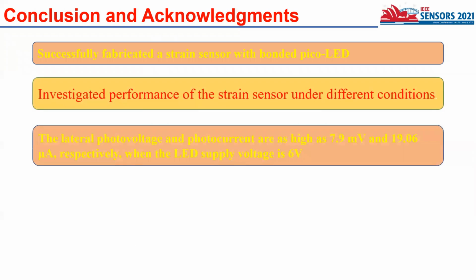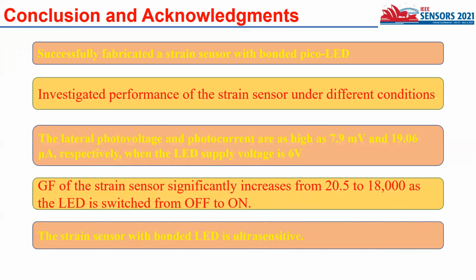We have successfully fabricated a strain sensor with a bonded LED, and we also successfully investigated the performance of the strain sensor under different conditions. With the strain sensor, using the bonded LED coupled with the tuning current, the gauge factor of the strain sensor has been significantly increased from 20 to 18,000.